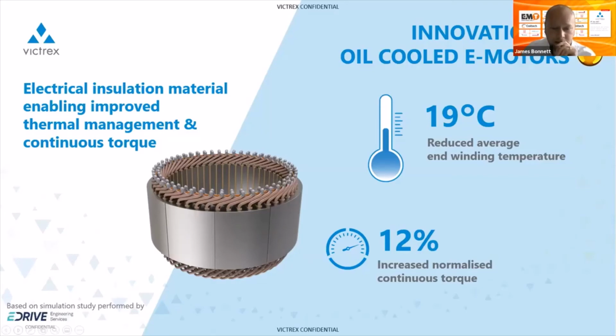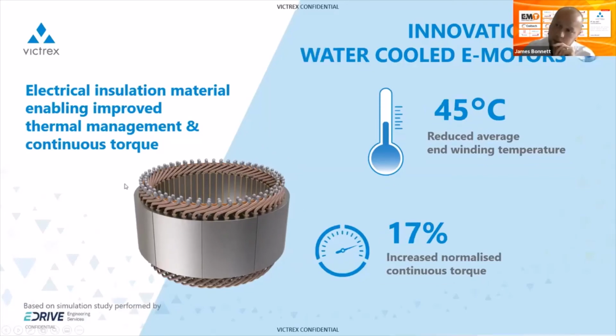In the second design, the eDrive engineers had modeled a water cooling system, which uses a water cooling jacket on the outside and draws the heat out through the electrical steel. In this model, the simulated benefits were even greater. They simulated a 45 degrees C reduction in end winding temperatures, and that would translate to an increased normalized continuous torque of around